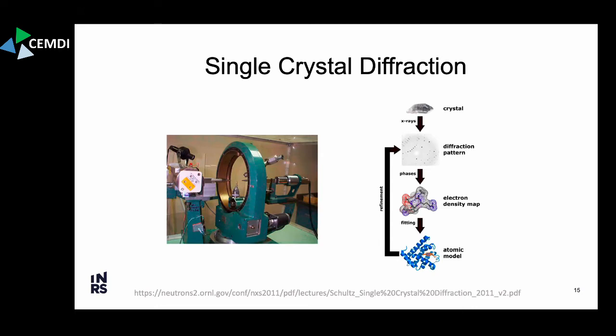And when you have a full 3D map of the intensities in reciprocal space, you can use phase retrieval, structure solution, in order to retrieve the electron density map. And then you try and fit that electron density map with an atomic model. So going from here to here, this is probably the hardest step, being able to really extract the phases. And this has been the push of crystallography for the past 100 years, developing methods to reliably extract the phases and to be able to solve for the electron density map.